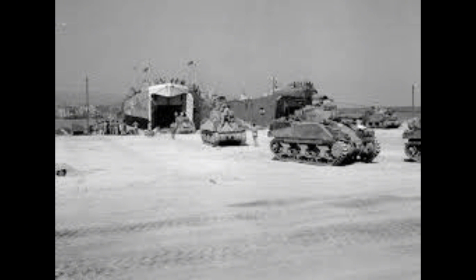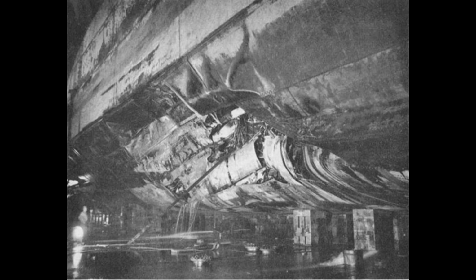Each time, she took more damage. Shell fragments opened a seam in the main deck plating. A near-miss bomb ruptured a ballast tank. Welding on the port bow door hinge area cracked from repeated shock loads. But none of these failures were catastrophic. The hull remained watertight. The structure maintained integrity. The ship kept operating. This was the pattern across the entire LST fleet at Normandy.